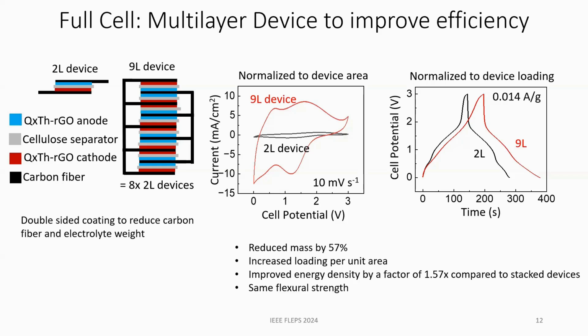So because we're able to increase the loading per unit area, we have a higher current output and a higher capacity. And we improved the energy density by 1.57 times compared to those individually stacked devices. And then because it's structural, it retains the same flexural strength as our 2-layer device.